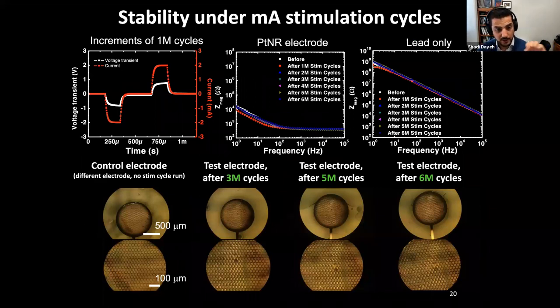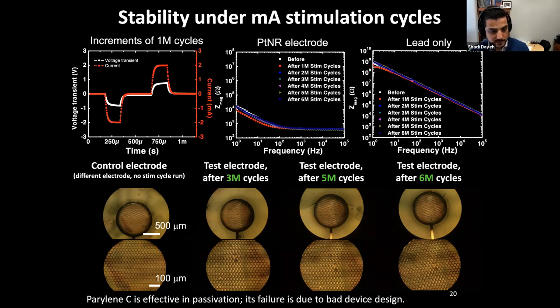Right, so they have low impedance. One can also pulse millions of cycles across these electrodes. Their morphology remains the same. Impedance doesn't change. And if we don't have an open contact, we are pulsing across just the dielectric, which is the parylene passivation. It doesn't open up. With proper design of the metal leads so that they have very low impedance, we avoid the corrosion of the metal leads, and these electrodes could work for millions of cycles.